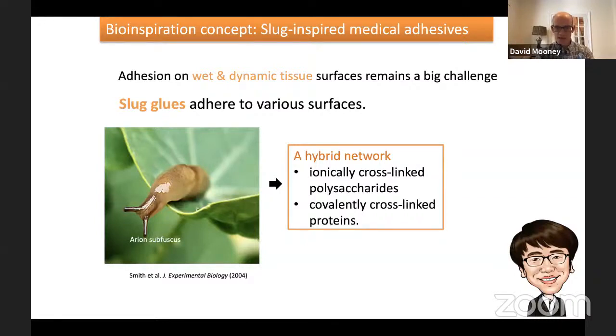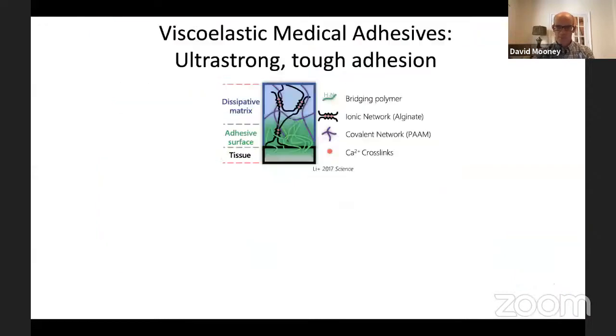When one looked at the composition of this mucus, it was a hybrid network comprised of ionically cross-linked polysaccharides and covalently cross-linked proteins. And Jianyu realized that this sure looked a lot like these gels that Xuanhe had been making that were able to dissipate so much energy. So he proposed that one could create new types of viscoelastic medical adhesives that would provide ultra strong adhesion by combining these, what we call tough gels, these dissipative matrices, with an interfacial material that could form strong bonds between the underlying tissue and the gel.